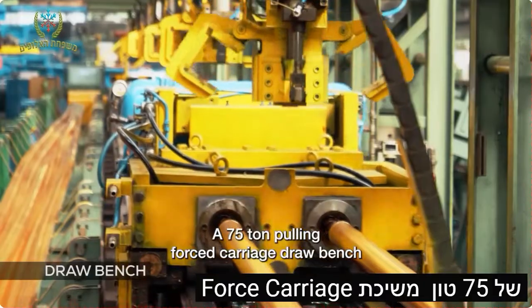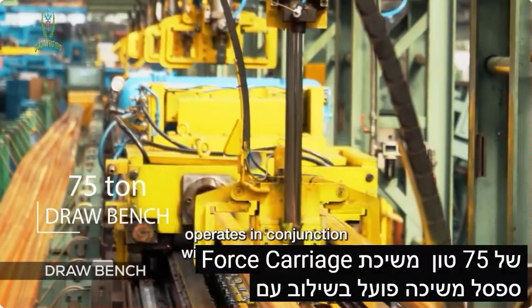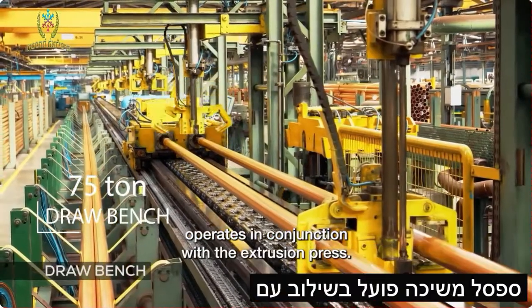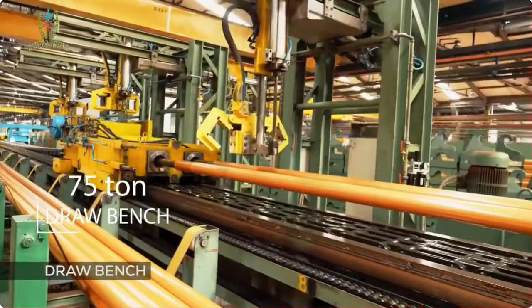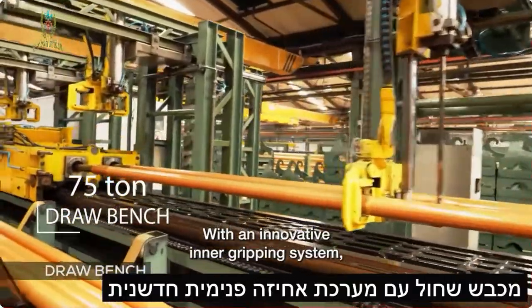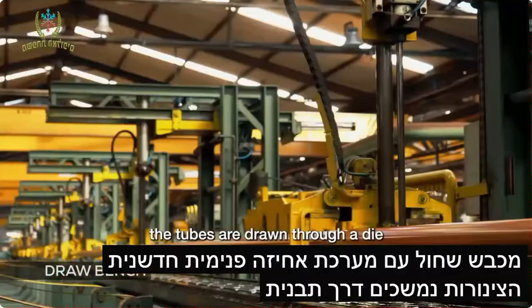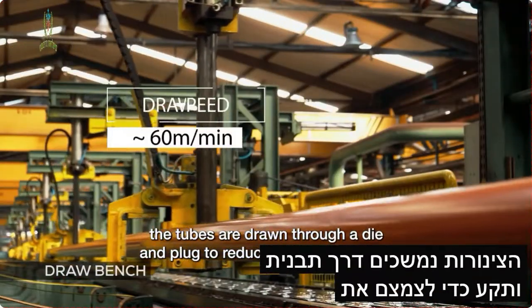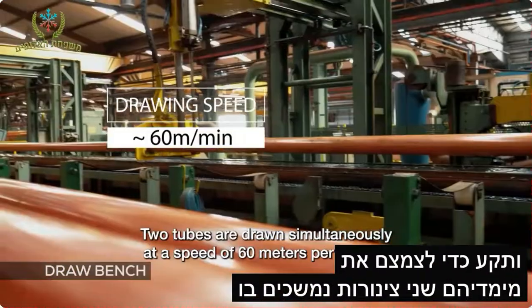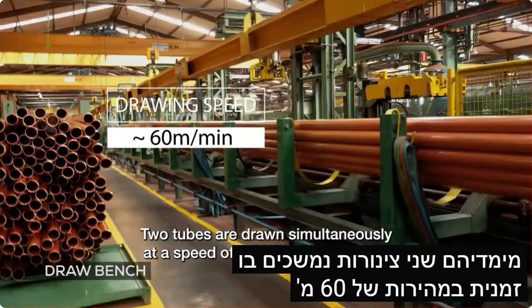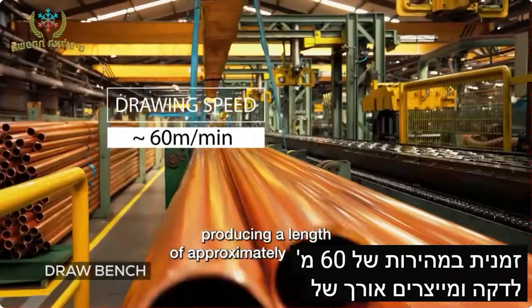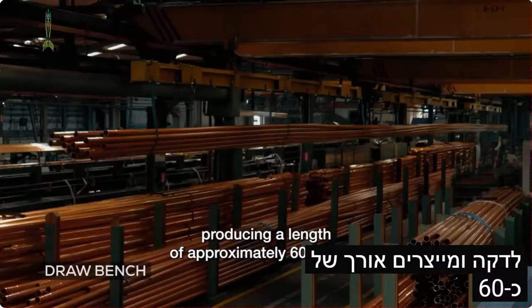A 75-ton pulling force carriage drawbench operates in conjunction with the extrusion press. With an innovative inner gripping system, the tubes are drawn through a die and plug to reduce their dimensions. Two tubes are drawn simultaneously at a speed of 60 meters per minute, producing a length of approximately 60 meters.